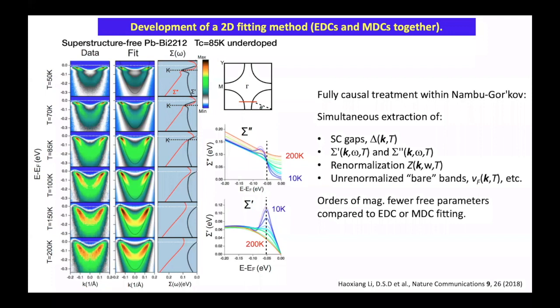There's lots of broadening, so sigma double prime at high temperatures is large, especially at deeper binding energies with a Fermi energy here. So let me show you, let's say I'm at 50 millivolts, somewhere around here. I'm at 200 K. My sigma double prime is over 100 millivolts. That's definitely non-quasi-particle-like. But at low temperatures and low frequencies, I have a drastic dropping of sigma double prime. Along with that, I have a peaking in sigma prime, and this happens because of causality, because of Kramers-Kronig. And these are constraints that go together. So maybe this is one of the main messages.